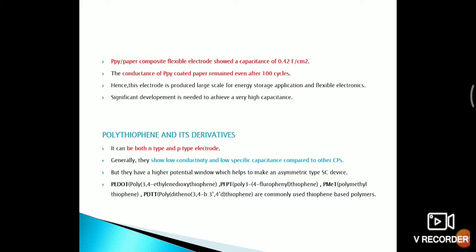Polypyrrole paper composite flexible electrode shows a capacitance of 0.42 farad per centimeter square, and the conductance of polypyrrole coated paper remained even after 100 cycles. Hence, this electrode can be produced on a large scale for energy storage application and flexible electronics. Significant development is needed to achieve very high capacitance in this area.